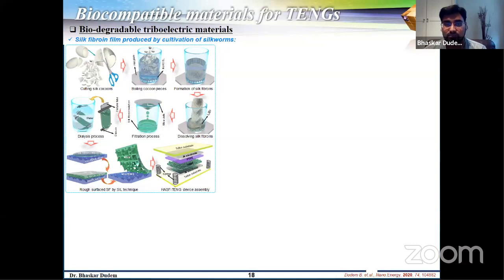So at the same time, finally, we have used a biodegradable material like silk, which can be cut into several pieces, and it makes a polymer using several chemical processes. And that polymer is used as a triboelectric positive material, and PTFE is used as a negative triboelectric material. In most of our work, we have used PTFE as a negative triboelectric material because it has an ability to grab electrons very easily, and it is noted as the best triboelectric negative material.